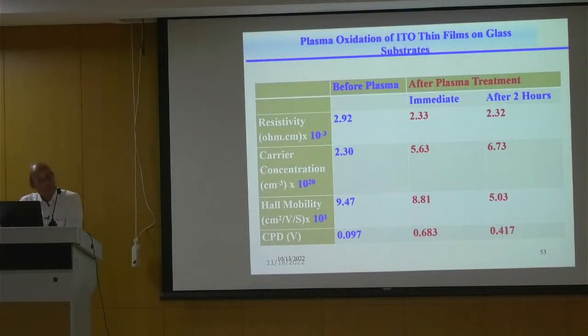Before plasma oxidation or plasma treatment, actually we used oxide plasma, and after plasma treatment, you see the resistivity goes from 2.92 to 2.33, and after 2 hours 2.32. Now you may ask me, if you are really a good measurement person, these results may not mean anything, because there is an error in the resistivity measurement. So maybe within the error of measurement, it may not be the property of the surface. Take carrier concentration, there is a small change, and this change is not really that great. If you take Hall mobility also, this way, that way, but the moment you come to contact potential difference, there is a drastic change, 0.097 volts to 683 millivolts and 417 millivolts.